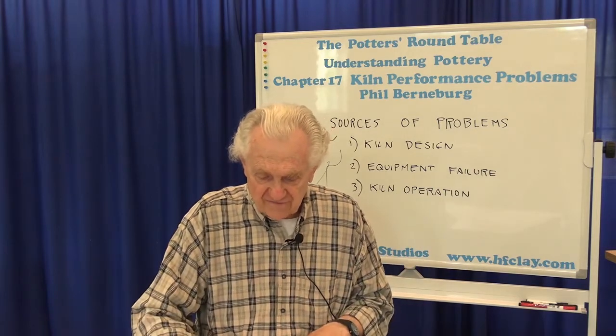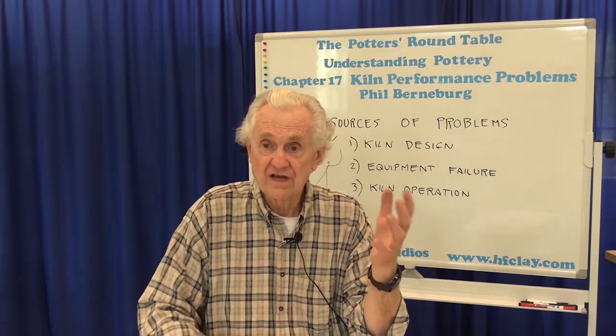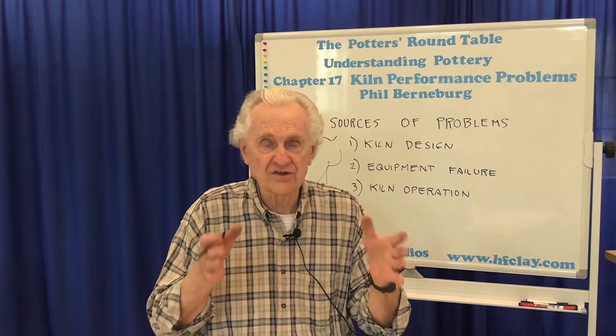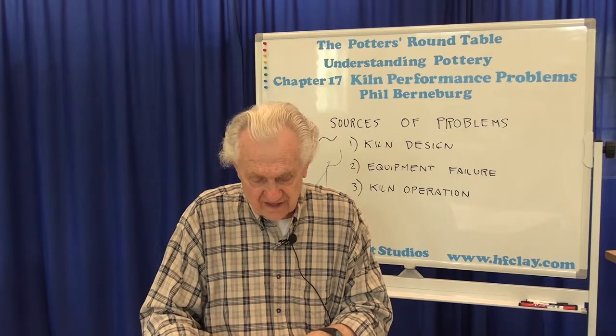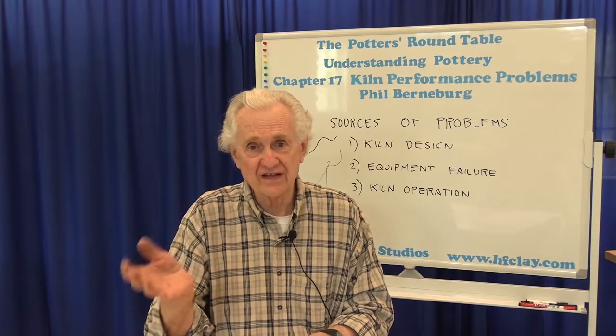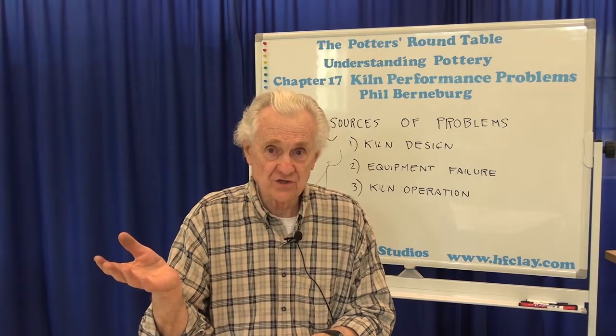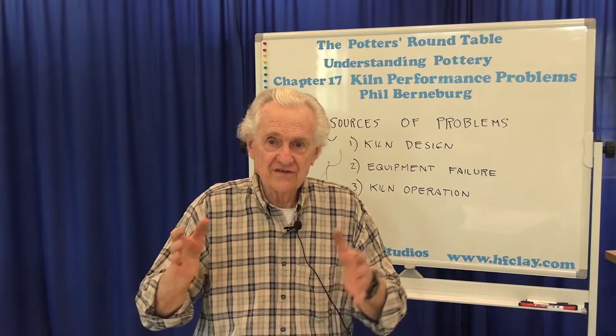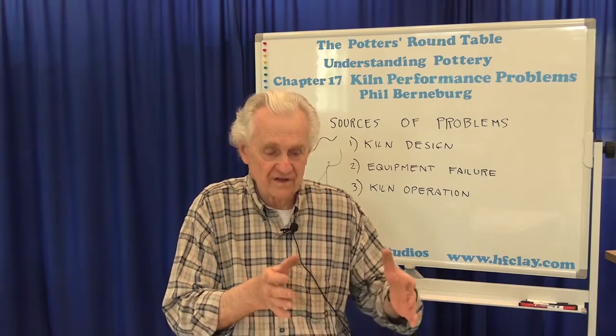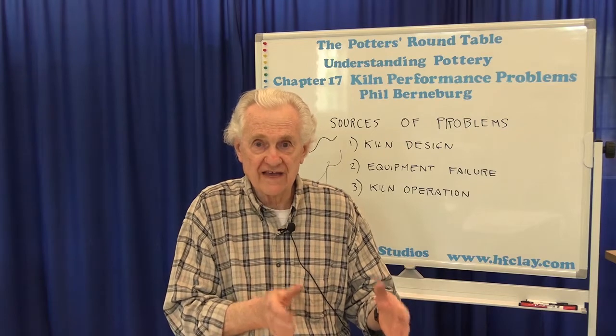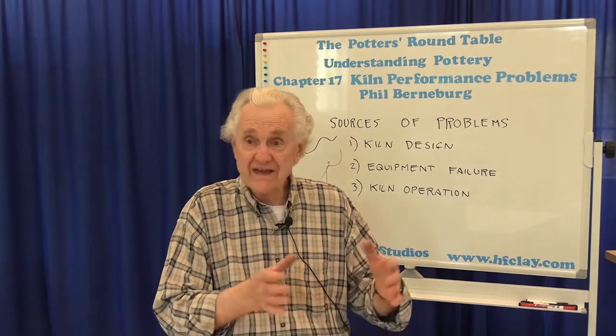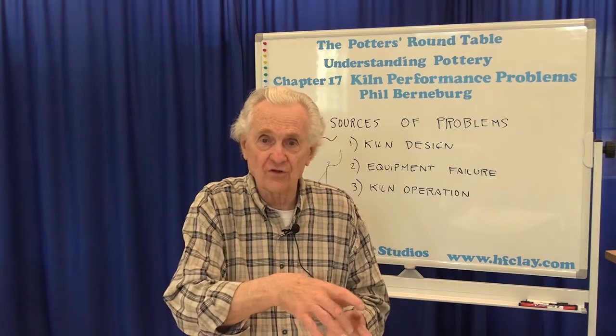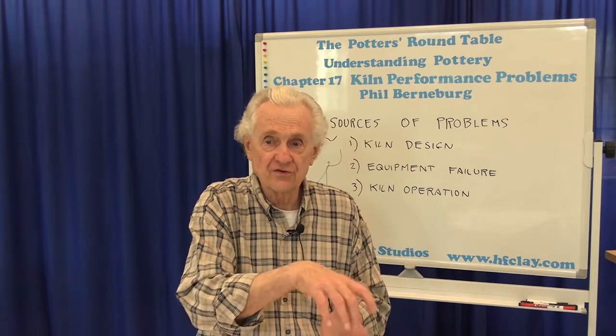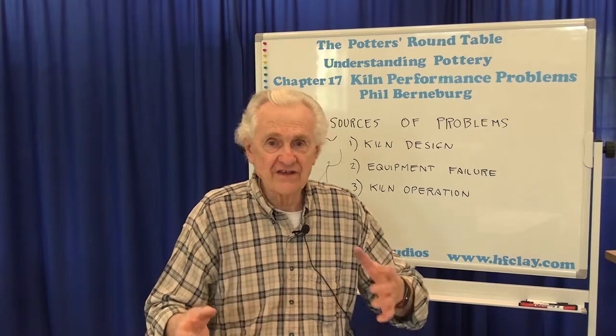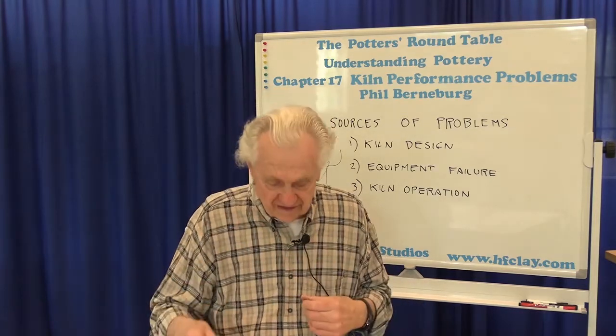Then you can also have design features. For instance, the firebox might be too small. They simply might not be able to hold enough wood to generate enough heat fast enough. Or it goes back to, it's always an air or a fuel problem. So if it's not a fuel problem, then maybe the chimney is too short. If the chimney is too short, then the draft that it creates, the pull on the firebox, is not enough to bring in enough air to burn the wood quickly enough. Or maybe the chimney is tall enough, but the air inlets, the holes where the air actually comes in, are too small to allow enough air to get in. And so basically the kiln is sort of choking itself and it can't get enough air.